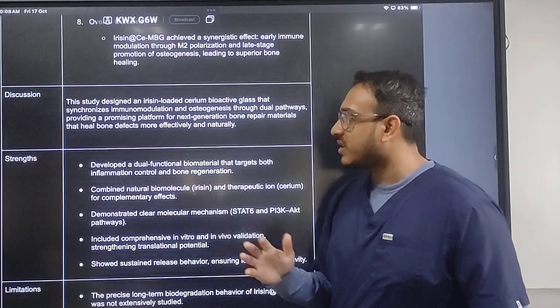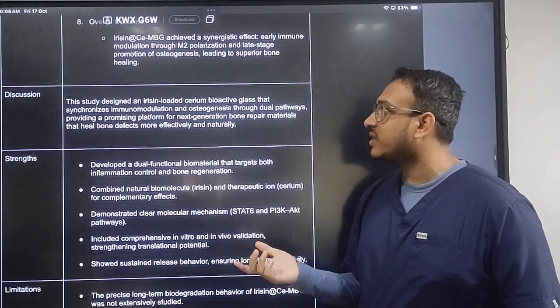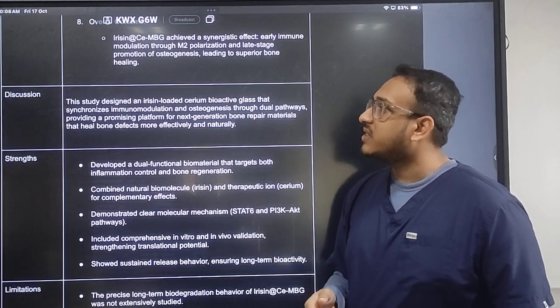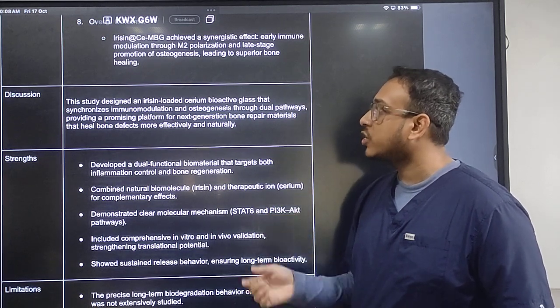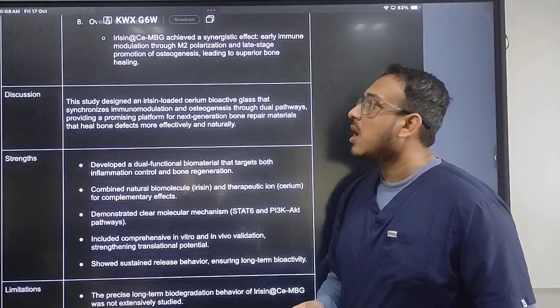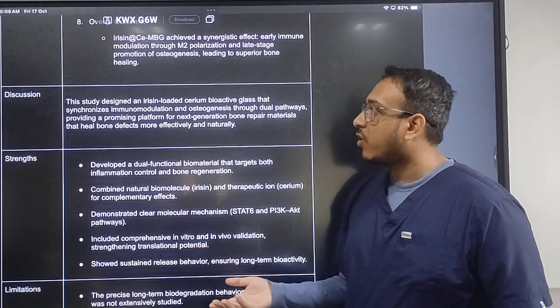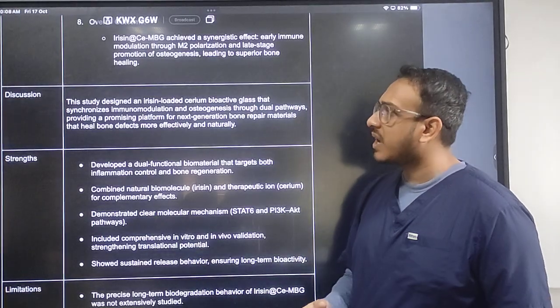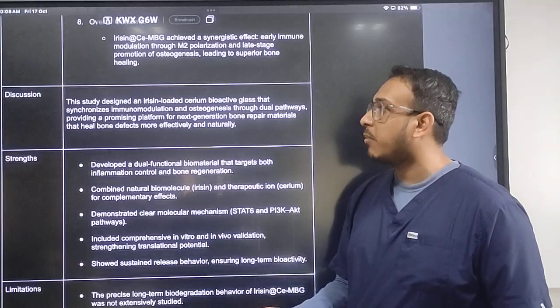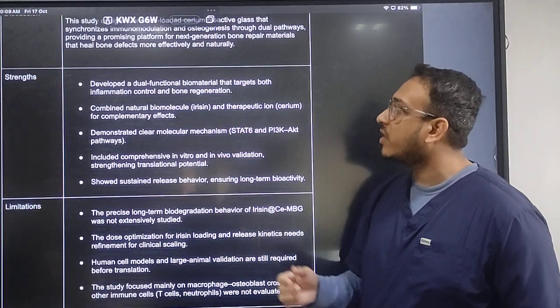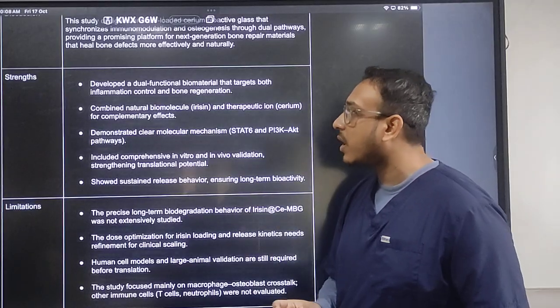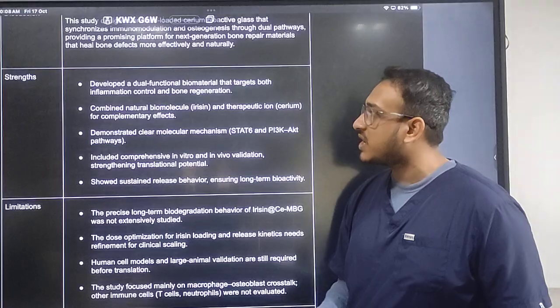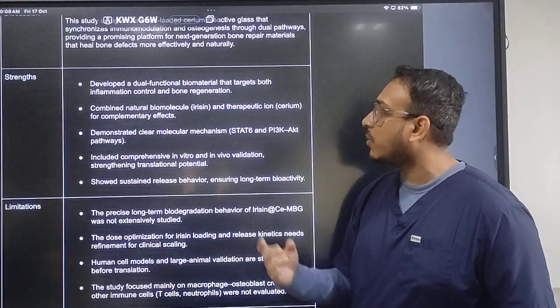So coming to the discussion, this study designed an irisin-loaded cerium bioactive glass that synchronizes immunomodulation and osteogenesis through dual pathways, providing a promising platform for next generation bone repair materials that can heal bone defects more effectively and naturally. The strength of this is that they developed a dual function biomaterial, as said before, to control inflammation and promote bone regeneration, combining natural molecules and therapeutic ions for complementary effects.